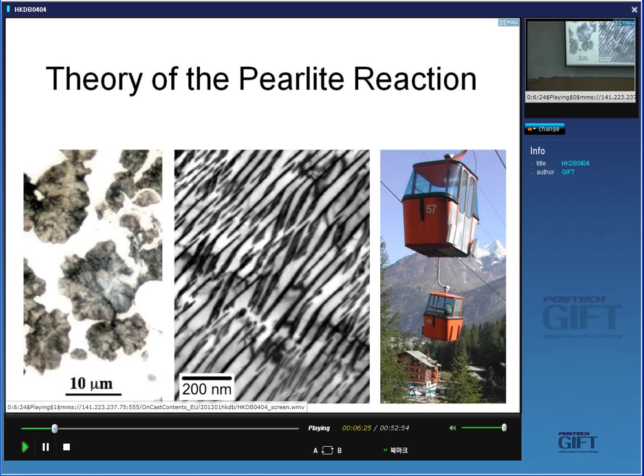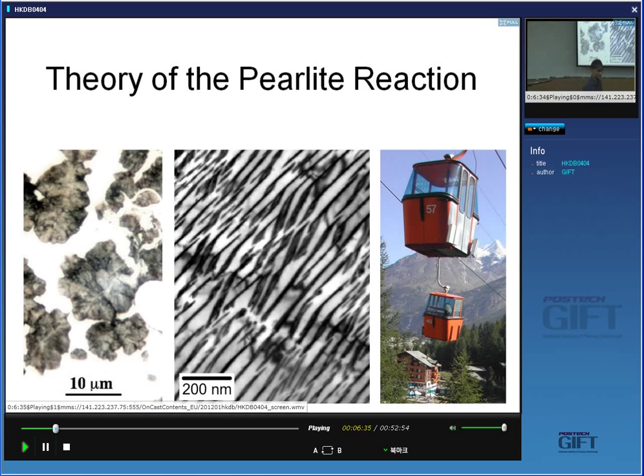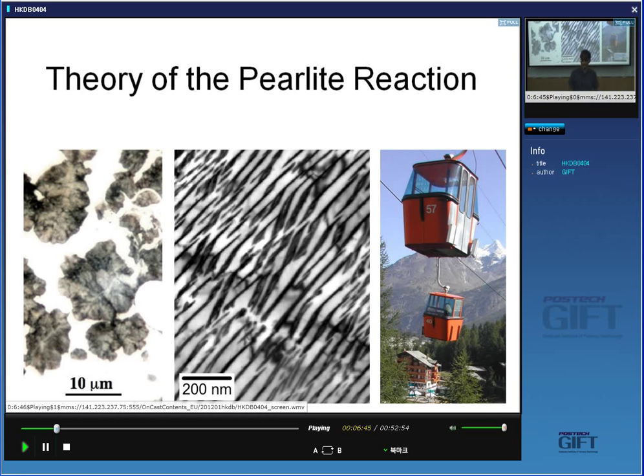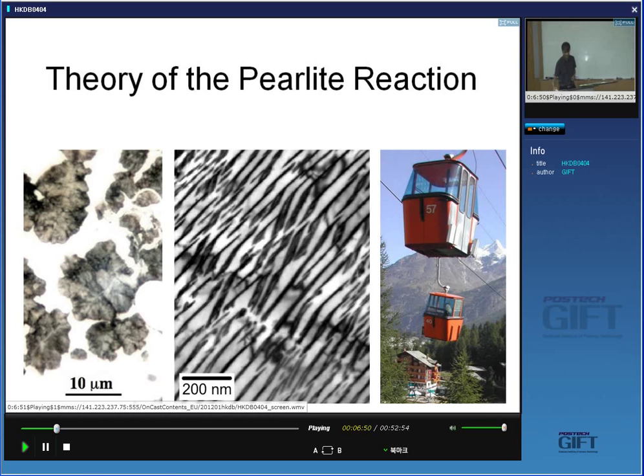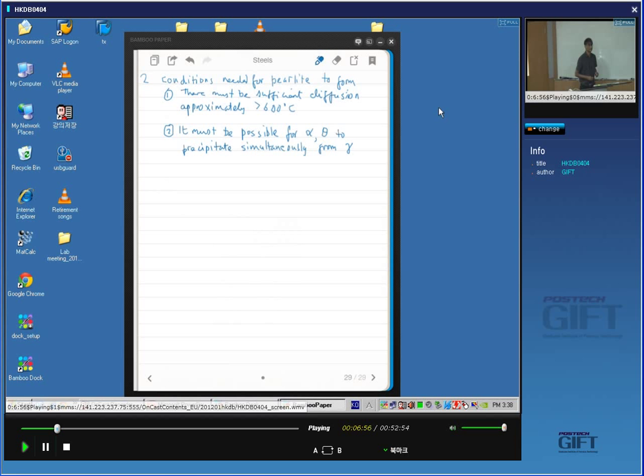In principle, you should be able to get to five gigapascals, but you require the ability to draw the wire a great deal, which means you have to have very pure steel. Generally speaking, the strongest pearlitic steel wires are of the order of three gigapascals — the stuff you see on suspension bridges, cables, and cranes. The spacing between the cementite and ferrite can be made very fine indeed, giving incredibly high strength.